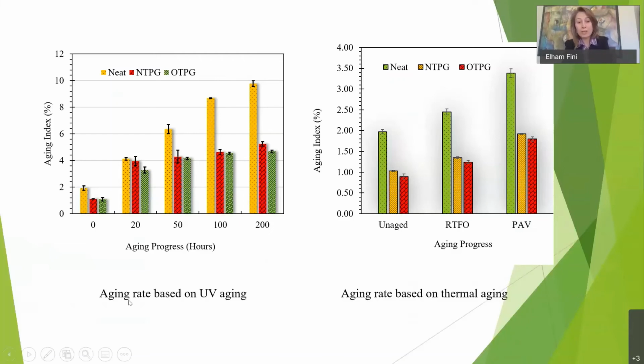So here we actually did the accelerated aging in the lab, and we exposed it to harsh UV, ultraviolet radiation. And that's actually pretty relevant in summer season. If you imagine the summer of Arizona, where I am from, it's actually quite intense. We get 320 days of sun, and it's pretty intense in summer. So UV aging actually makes roads get damaged or age pretty fast. So we did that in the lab, and we compared the neat with the plastic ones. Here you can see the ones that have plastics, regardless of what type of plastic, aged much less.